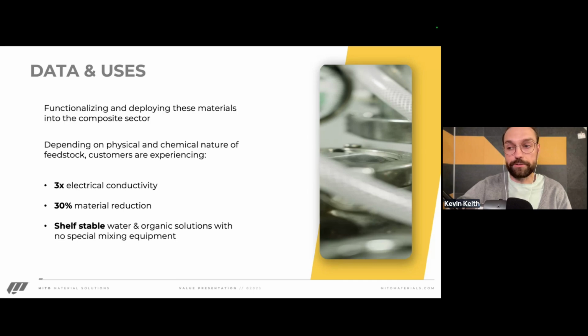So, we're able to supplant a lot of different other additives that were primarily being used to slightly increase conductivity, but it added a whole bunch of weight. So we're talking, you know, 0.02 to 0.2% loading by weight into the resin, and you're getting these conductivity increases. With these other materials, we're able to reduce materials by 30% with 0.1% by weight of our materials.